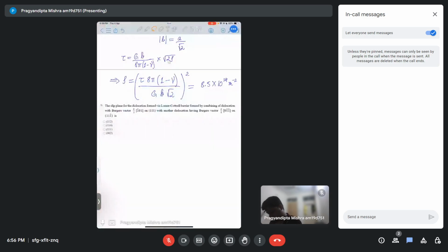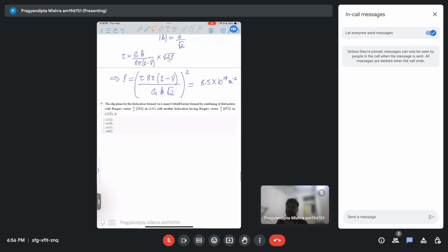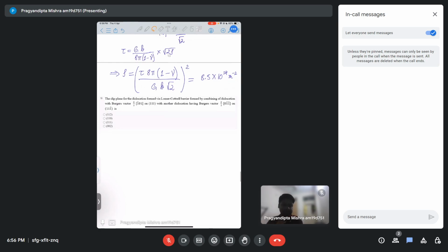Okay. So they have told the slip plane for the dislocation formed via Lomer-Cottrell barrier, formed by the combination of a dislocation with Burgers vector A by 2 1 bar 0 1 on the 1 1 1 plane with another dislocation having Burgers vector A by 2 0 1 bar 1 bar on 1 1 1 bar, is what? Okay. So how do we do this? Very simple steps we have to follow. First, there are a few things we have to understand.